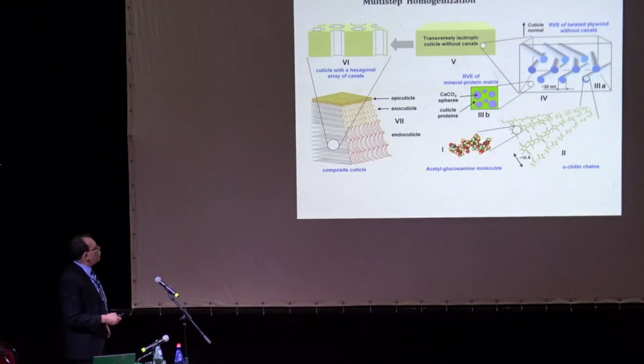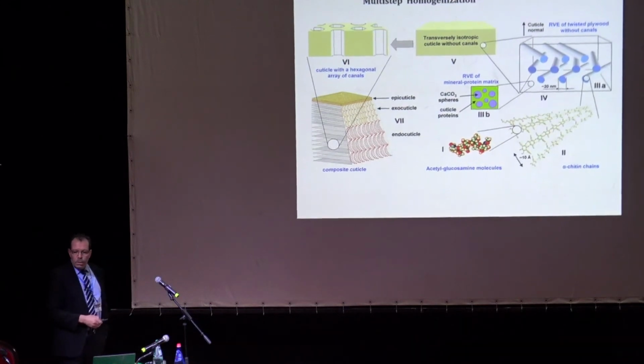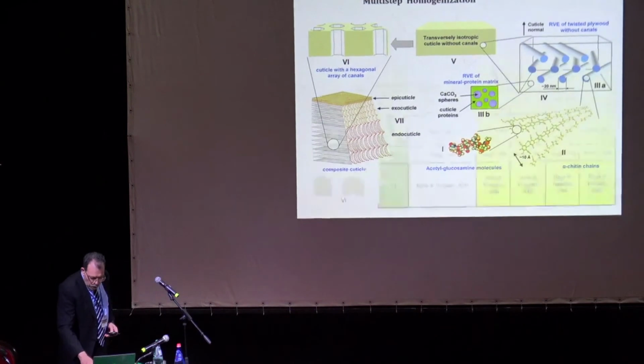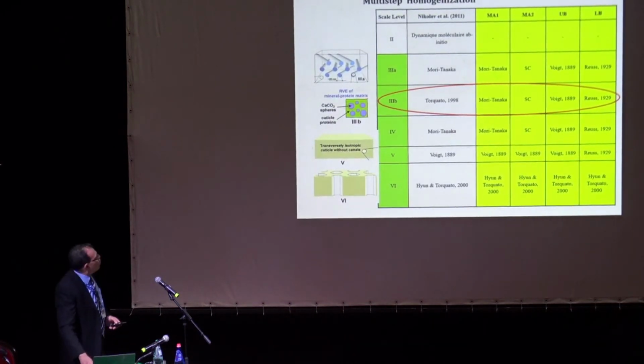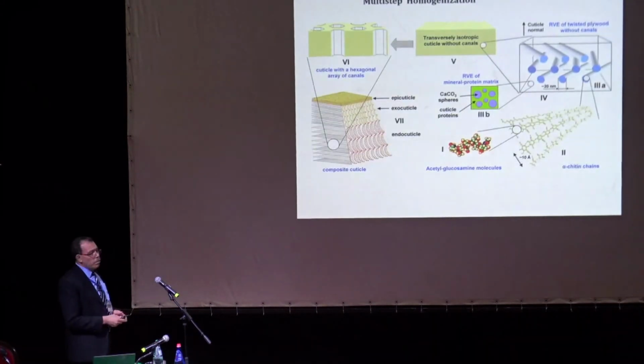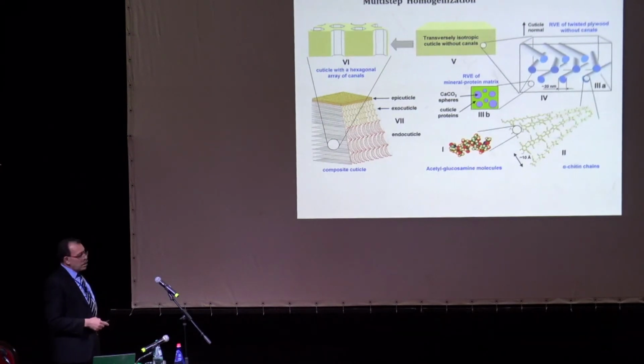So just to show you the multi-step homogenization, first we need the properties at this level here of the chitin chains. Well, we used some work by one of our colleagues with whom we collaborate to do this work. His name is Nikolov, from Max Planck. And they also did experiments at Max Planck, and we used their experimental work. So they use molecular dynamics to get the elastic constants here, okay?